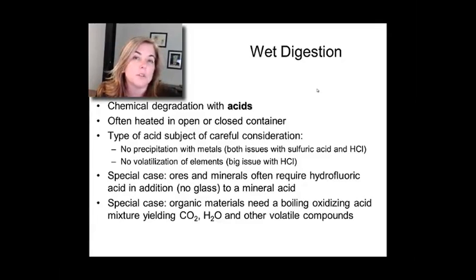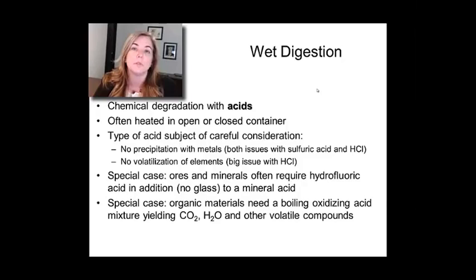Some of the common features that I certainly know from experience about wet digestion: you almost always have to heat it. Wet digestion can take a really long time. And so heating, finely dividing your starting material is really helpful. The other thing that's interesting in the acid choice is you don't want to use acids that could precipitate certain metals. So say you have a sample that has a lot of barium in it. Well, if you added sulfuric acid, you're going to precipitate barium sulfate, and that would be a poor choice.